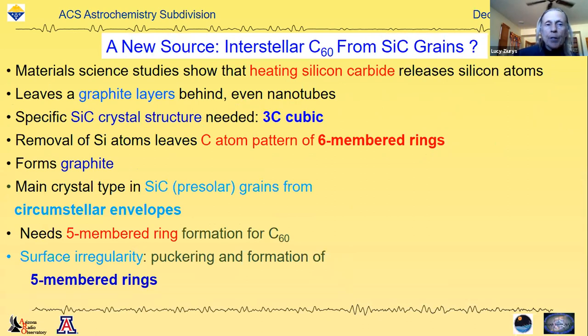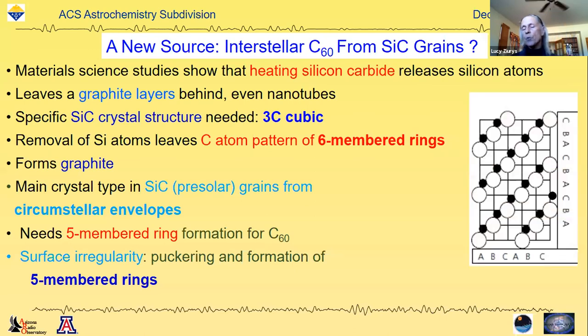our collaborator in the material science department. And we found out that for many years, it's been well known that heating silicon carbide releases silicon atoms and forms graphite. In some cases, it even forms nanotubes. But it typically requires a specific SiC crystal structure, which is called 3C cubic. 3C cubic looks like this. The silicon is the larger atom, the carbon is the smaller.